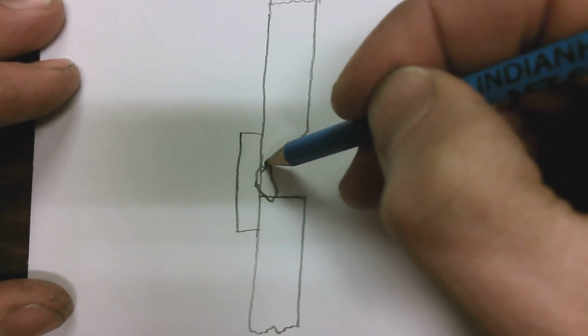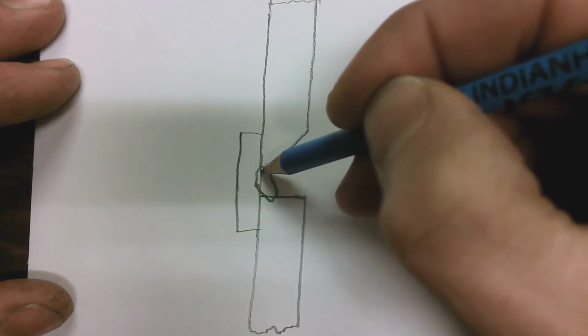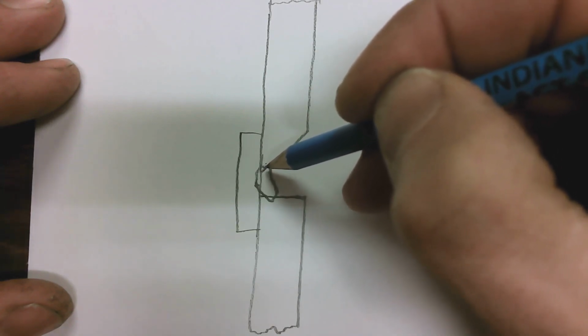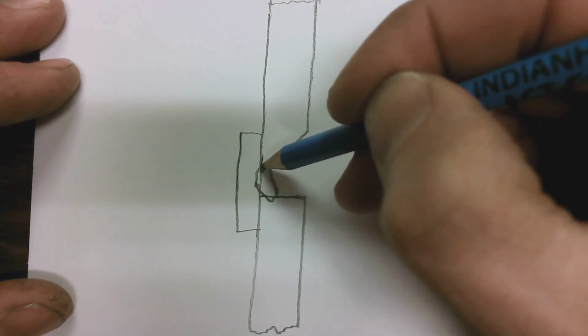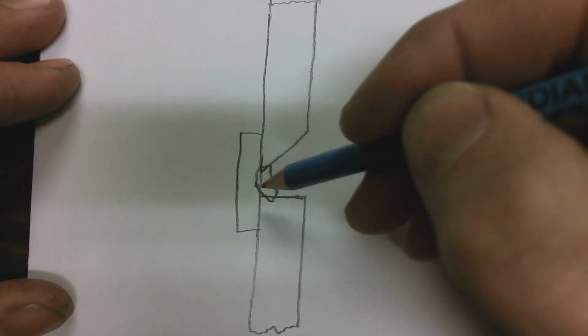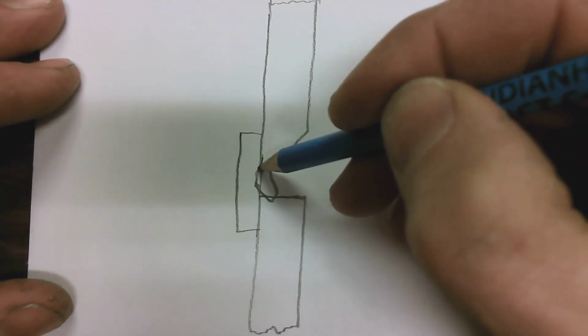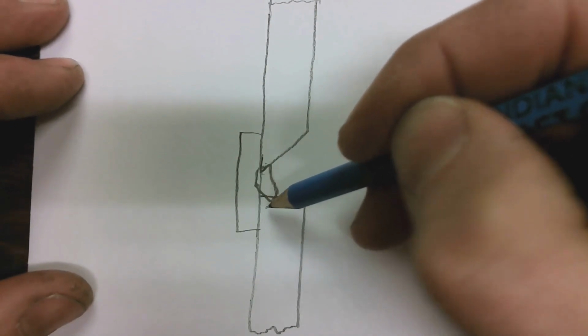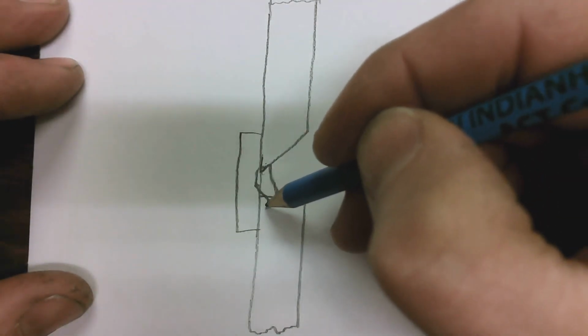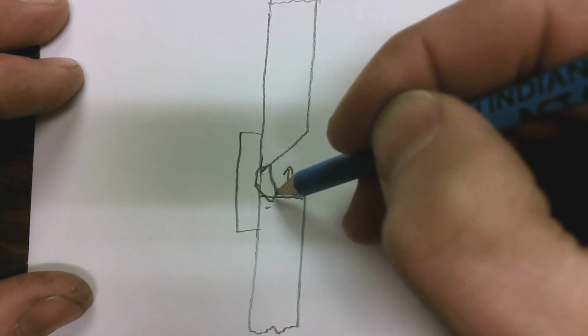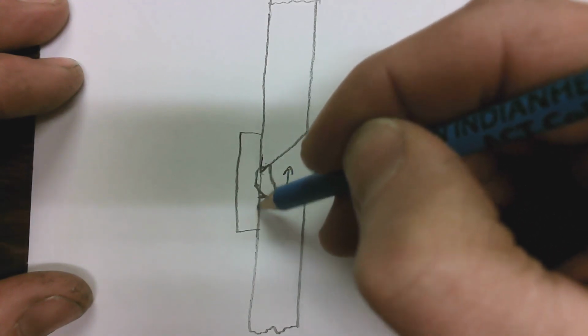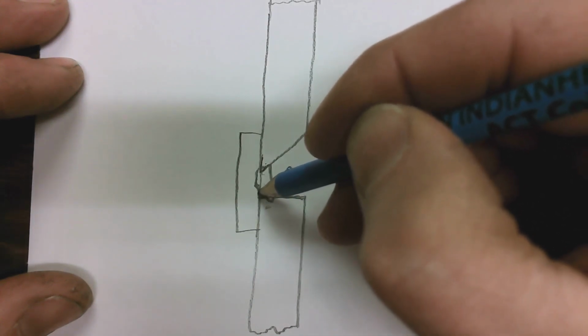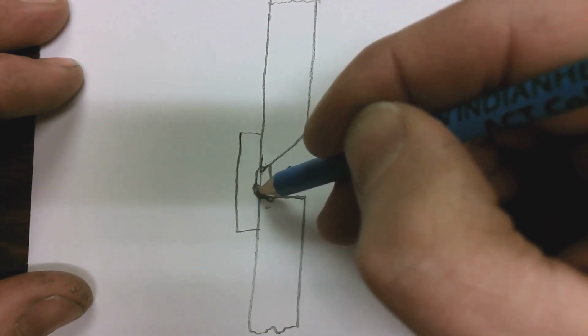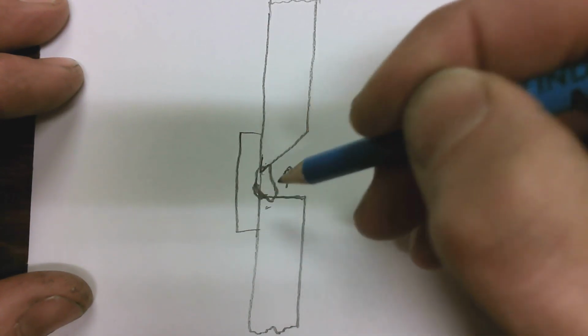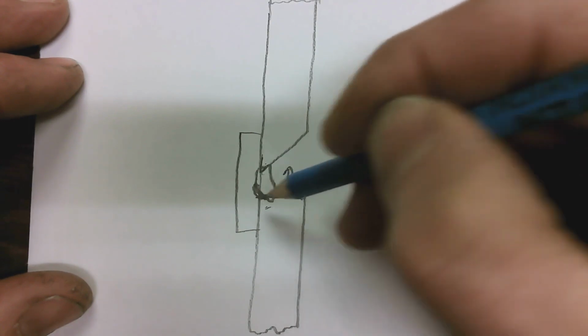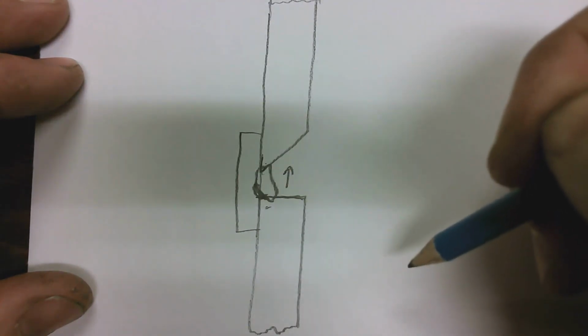where again they were tying in pretty nice to the top piece. Heat rises, so that's a bonus. Plus we've got a thin point right here which is going to melt fast. So good tie in there. Tie into the backing strip. The problem is this thick piece of metal, with the heat rising and going away from it, this edge right there never got melted fully. The metal might have been just kind of laying on top of it. We saw that tiny thin line there, but it never actually fused in at that particular spot.